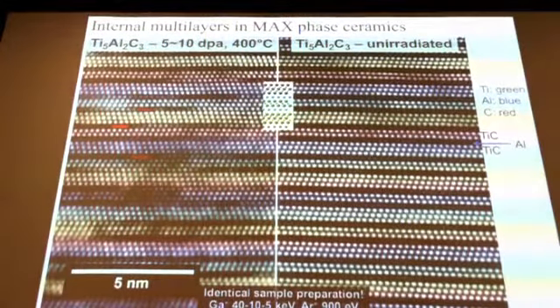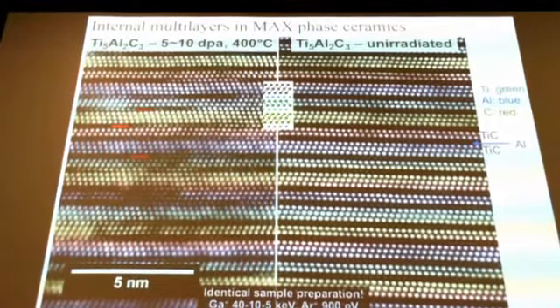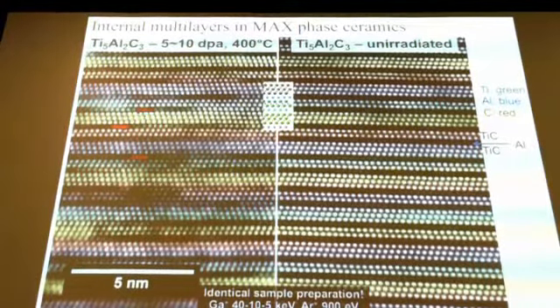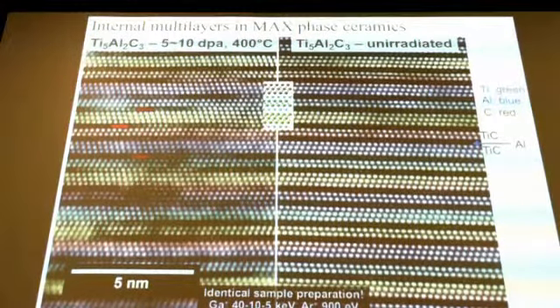There are many other ways that one can imagine coming up with these very high sink strengths. So there's work at Los Alamos and other places performed over the last few years looking at nano-layered structures that introduced very high densities of interfaces, and that proved to be, in certain cases, very effective ways to cause point defect recombination.